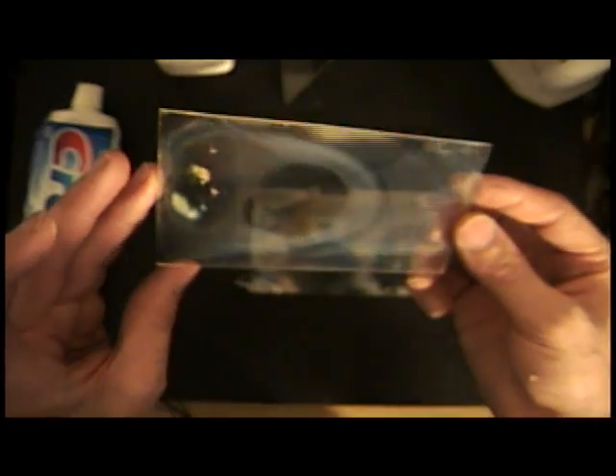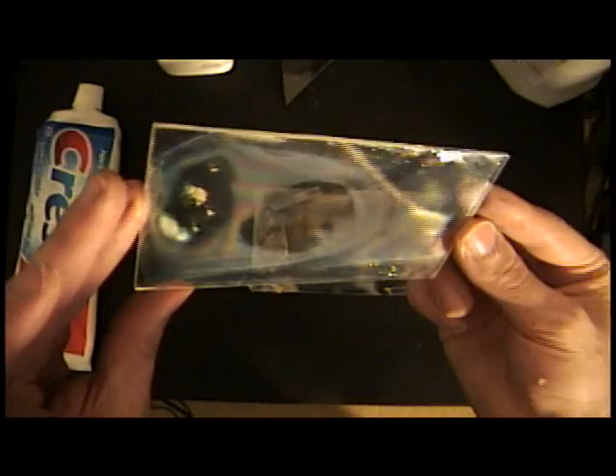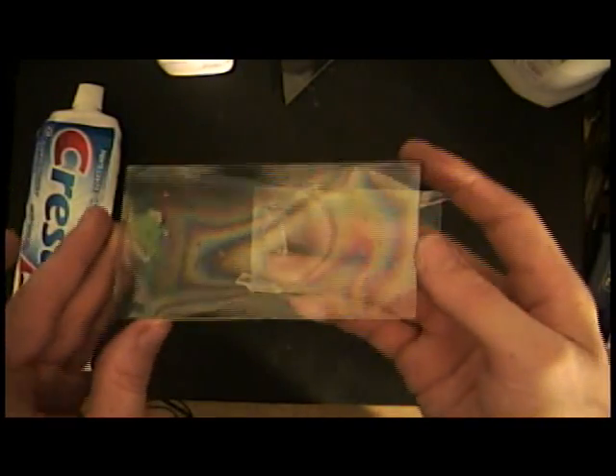The stannous chloride will decompose and form a tin oxide layer. You can see the rainbow color on the glass here, which becomes conductive. Tin oxide is a wide bandgap semiconductor.